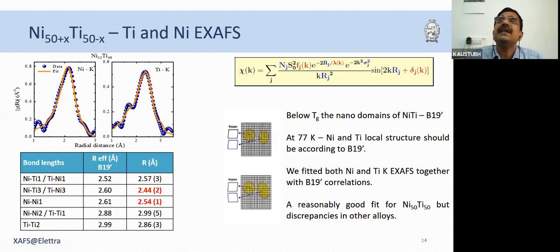So we thought we should fit the two K-edges together to minimize the dependency of parameters and control everything. So we did that. We could get a reasonably good fit, but you can see here the parameters that we got, especially the bond distances, were far off from what was expected of B19 prime. And we did not have any explanation for these numbers, which were very different from what we were supposed to get. So we thought we should go back to the drawing board.